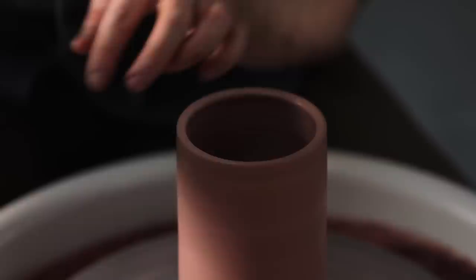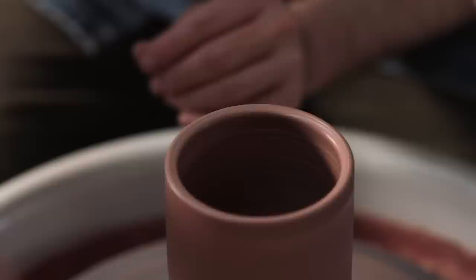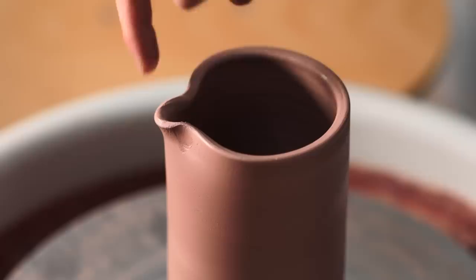I'm going to begin by showing you two types of rim that perhaps aren't suitable for this first spout pulling technique. All the tools you're going to need to make spouts are two digits that are kept dry, and another one which is dipped in water, which is going to stretch the clay out between a dry finger and thumb held sturdy on the wall of the pot to brace it, as the wet finger stretches the lip out. In this instance, I've left a rim that is too thick for stretching and pulling the spout. Due to its initial thickness, even after the clay has been pulled out, the pouring lip itself is still going to end up being relatively thick and therefore quite rounded. And ideally, to achieve a pour that's neat and doesn't drip too much, we want an edge that's sharp.